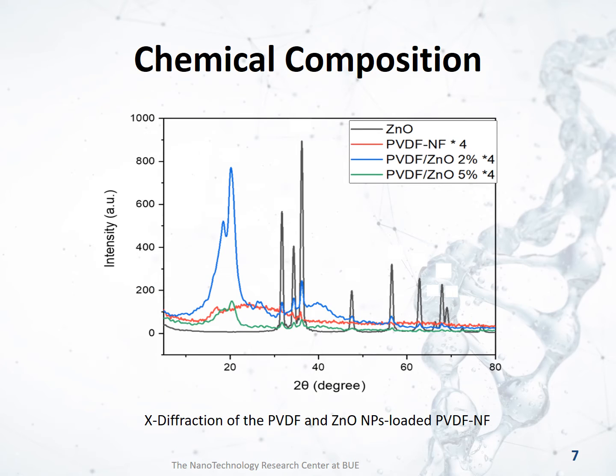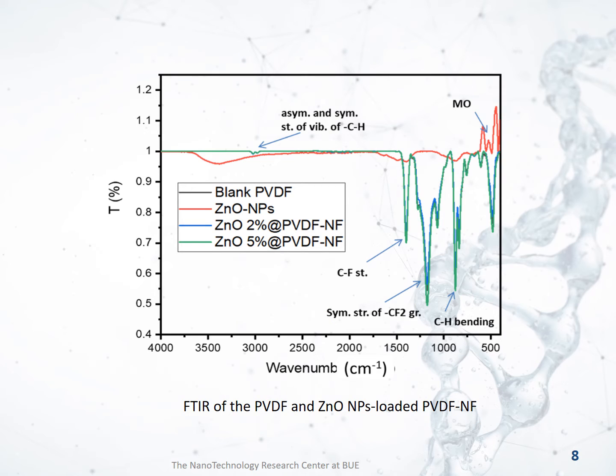To ensure that the zinc oxide chemical composition was not affected by the electrospinning process, we studied the XRD of zinc oxide and zinc oxide loaded on PVDF polymer. And we ensured that the phase is still the same, with no change in the peaks, as well as no impurities appearing. Also, we conducted FTIR analysis to ensure the chemical composition of the prepared material was not affected after the spinning.